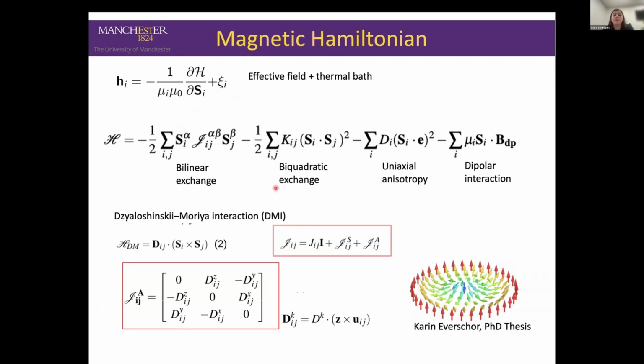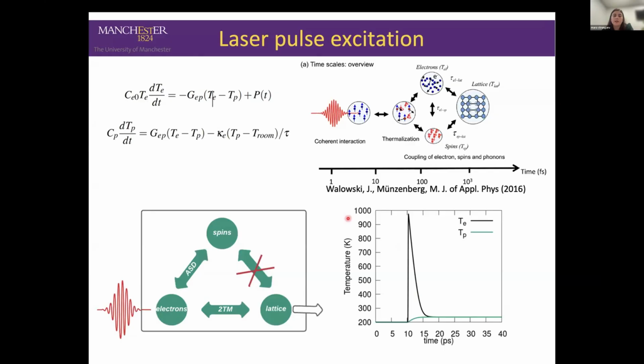Depending on the material properties, the Hamiltonian can be extended to include multiple contributions. In the simplest case, we have the exchange, and the exchange matrix can be developed in such a way as to include the antisymmetric terms, also called the Dzyaloshinskii-Moriya interaction terms, which give rise to skyrmions. We can have higher-order exchange interactions, as shown here by the biquadratic exchange, and many other energy terms. And one aspect we've been looking into in the past year is the interaction of magnetic systems with laser pulse excitations and how we can use that for technological applications.